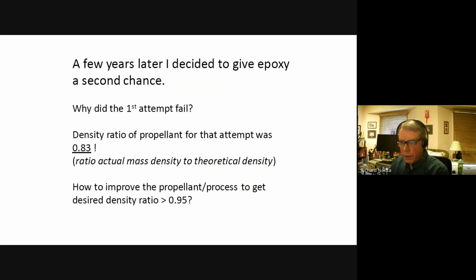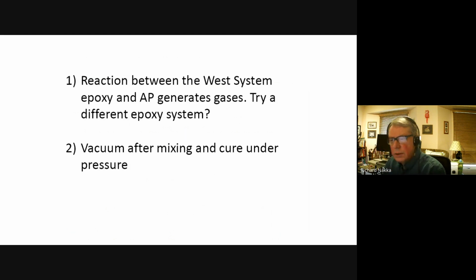So why did the first attempt fail? Well, looking back in my notes, I saw that the density ratio of the propellant that I made was 0.83. In other words, the ratio of the actual mass density to the theoretical was only 83%, which means that the propellant is very porous or full of air. And you really should have a density ratio of at least 95% with the minimum amount of porosity. So obviously there was some kind of reaction between the West system epoxy and the AP.